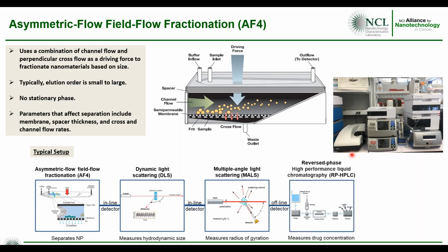Here's a picture of it in our lab. So here we have our AF4 channel in the middle. We have hooked up to this our UV, we have a MALS detector, RI, and inline DLS, and that's shown down here. We separate with AF4. We use inline DLS to measure hydrodynamic size, inline MALS to look at radius of gyration, and finally we do a lot of offline collection coming off the AF4 and do reverse phase HPLC on those fractions to measure drug concentration.